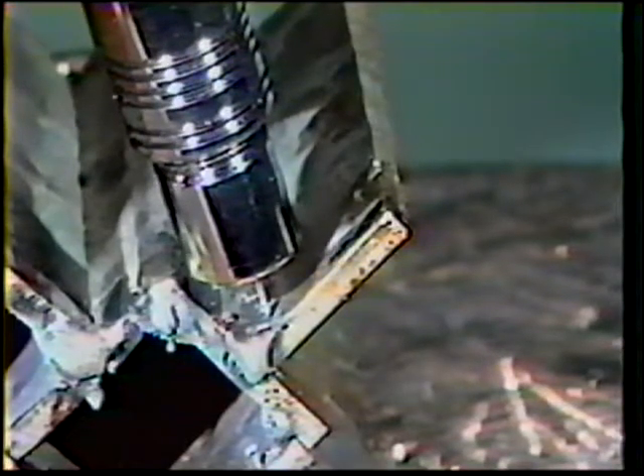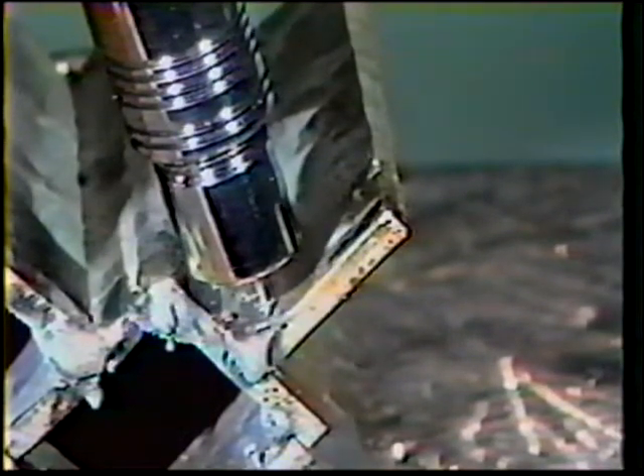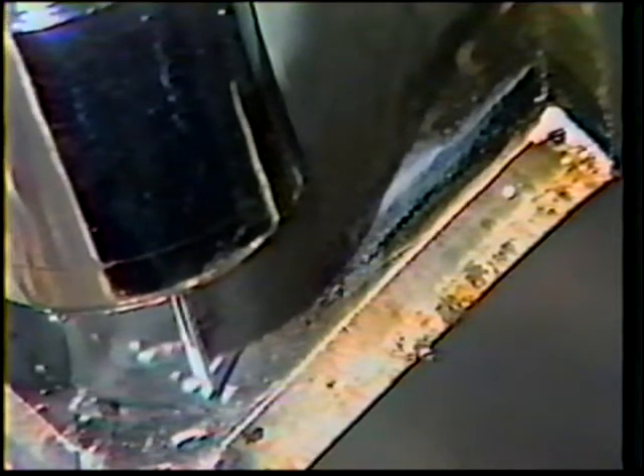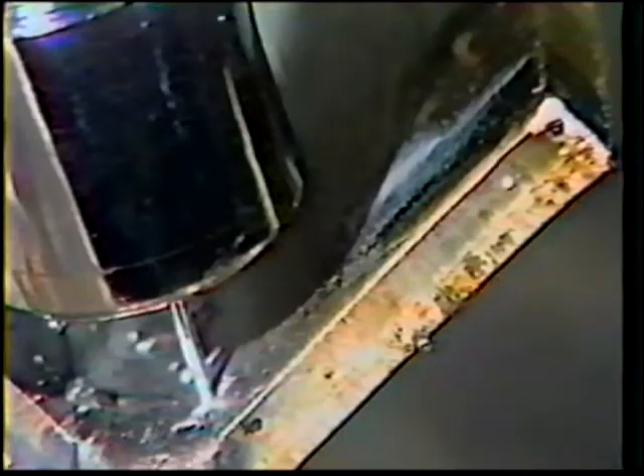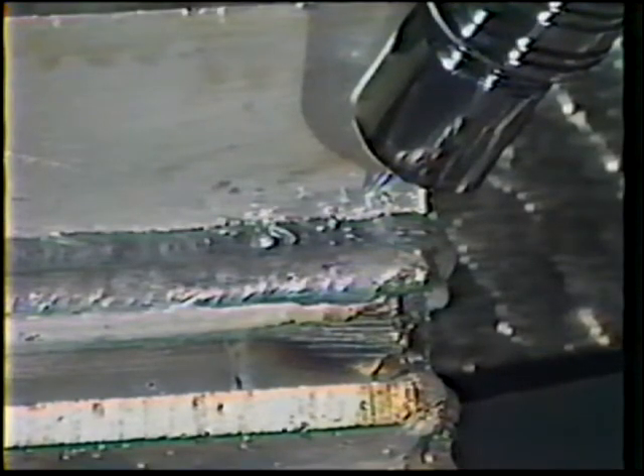For the second pass, position the gun with a 50 to 60 degree work angle, directing the electrode onto one toe of the first bead in order to overlap it about two-thirds of its width. The travel angle is again 20 to 30 degrees push. Move evenly along the joint. Do not hesitate while traveling or melt through can occur. The finished second pass should not exceed 3/8 inch in width and should be flat to slightly convex, overlapping the first pass by two-thirds. Deposit all the second beads on all workpieces before beginning the third pass.